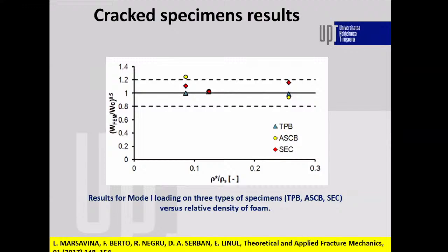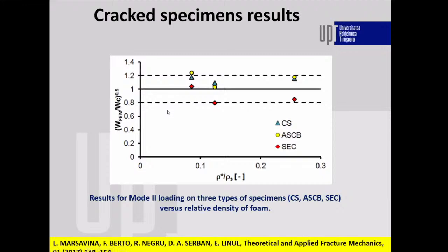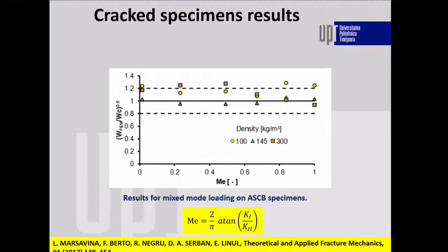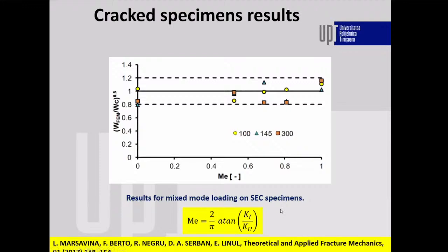We expressed the results as the square root of the finite element strain energy density over the critical strain energy density. This was plotted versus the relative density for mode 1, for 3-point bending, asymmetric semicircular bend and single edge crack specimens. In mode 2, for compact shear, asymmetric semicircular bend and single edge crack specimens. Then for the two mixed modes, we have the different densities and the mode mixity parameter. These results are from the asymmetric semicircular bend, and these are for single edge crack specimens.